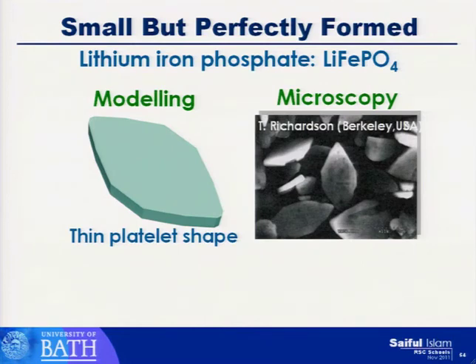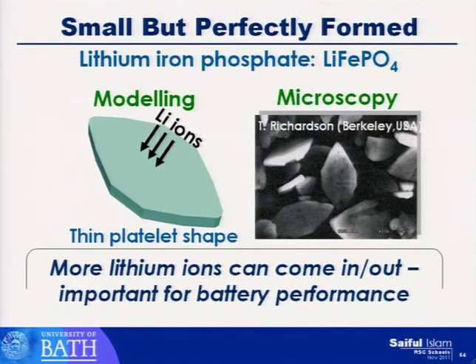Well, the reason why it's important is that the big face on that plate-like crystal is perpendicular to the lithium ion channels. So the lithium ions are actually coming in and out of that big face, which is very important because you want as many lithium ions to come in and out as possible, as fast as possible. The big issue in terms of charging and discharging is how fast you can do it. Obviously, all of us ideally would like to just plug in our phone and get it charged up within a minute. There are problems with that, and that's related to this idea of lithium ions coming in and out. So more lithium ions can come in and out with this large face, and it's important for battery performance.